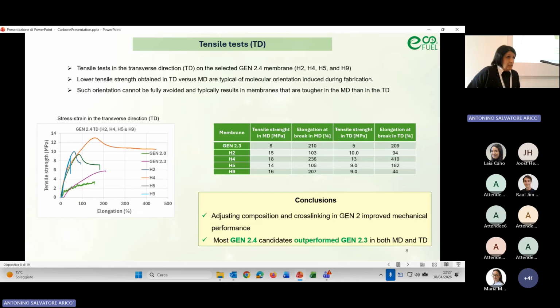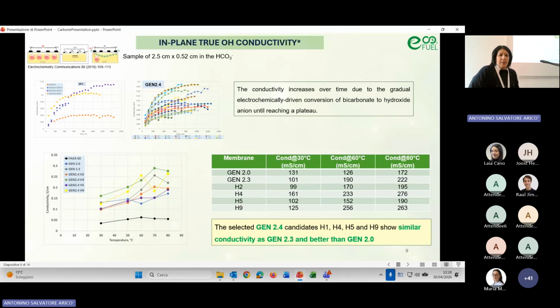in the transverse direction. We can see from the graph that of the membranes H2, H4, H5, and H9, only the H4 reached the best tensile strength, approaching the 20 megapascal in both directions, while the H9 has a different behavior, due probably to an orientation of the molecular chains or some anisotropy in the membrane. Then the ion conductivity was carried out.